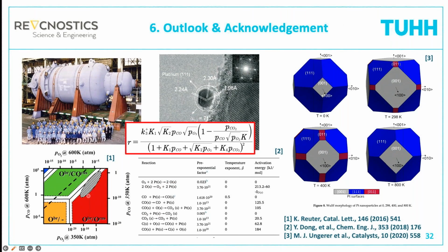We can even compare to phase diagrams that have been calculated, for example, by Karsten Reuter, and compare what surface adsorbates we have under which conditions in the reactor. And you can even start to include catalyst dynamics, because you can do a Wulff construction for every condition that you have locally in the reactor, determine the thermodynamically stable crystal shape, and then formulate microkinetic models for these different crystal shapes. So this opens up quite a lot of possibilities.